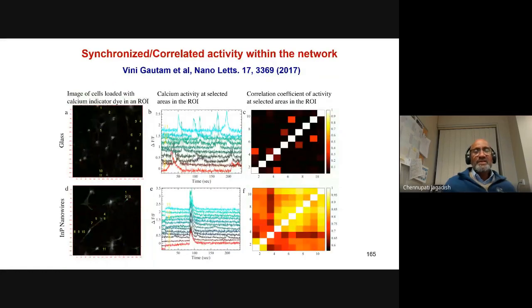Again, see, Vini compares these ones which are grown on the glass substrates and then the indium phosphide nanowires. As you can see, the first one, the glass substrates, shows a change in fluorescence as a function of time. You can see that different neurons are firing at different times. There's very little correlation, and the correlation is very, very small when you really look at this communication between